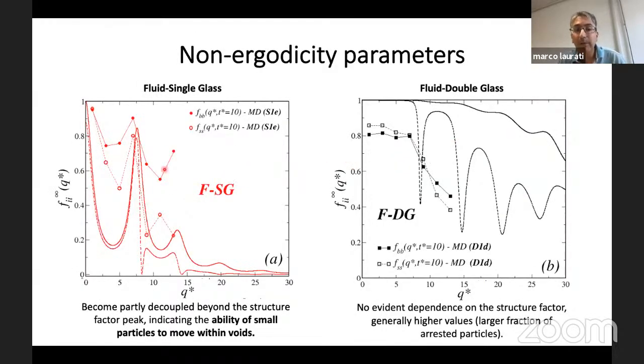Similarly, one sees this sort of decoupling in the non-ergodicity parameters, especially in the fluid to single glass transition. One sees that beyond the first structure factor peak, the non-ergodicity parameters of the small spheres start to lose their relation with the structure of the large particles matrix.